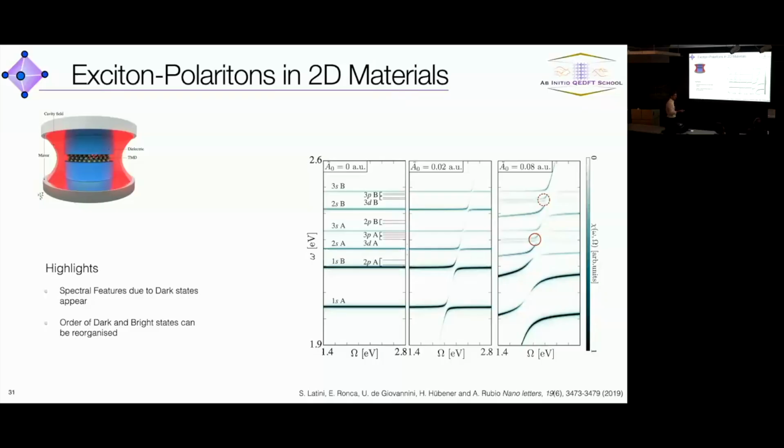So now these d-like states are the ones you would expect for a hydrogen atom, but they are dark usually, so you cannot excite them because of symmetry. The dipole matrix element just doesn't work. But because you're coupling the S with a P and then back to a D, those transitions are allowed. And then you can actually brighten this transition up and see it in a response experiment in strong coupling.